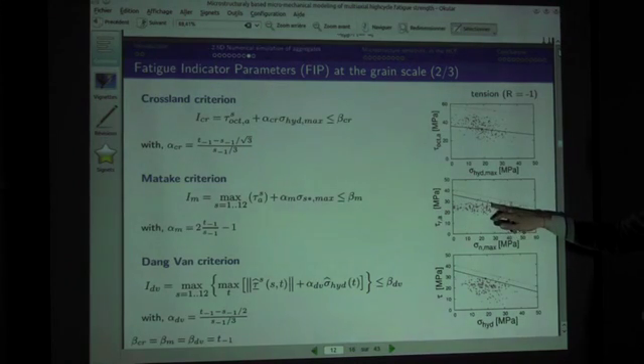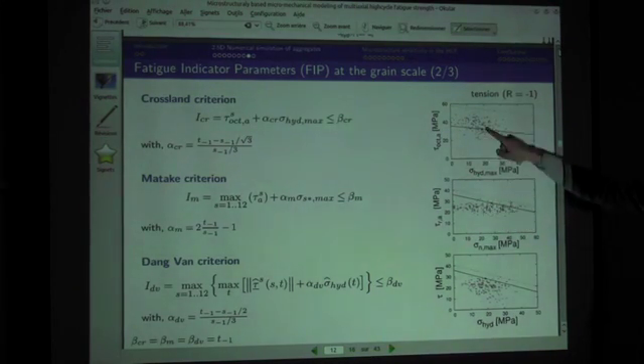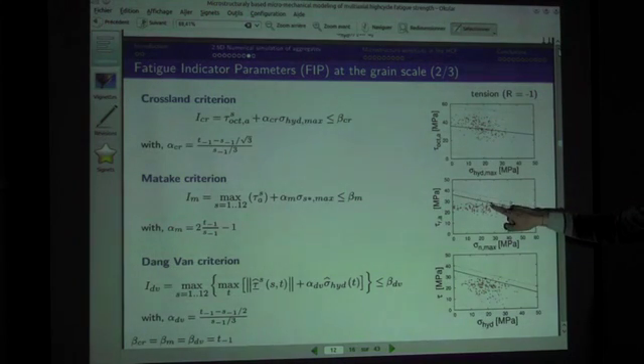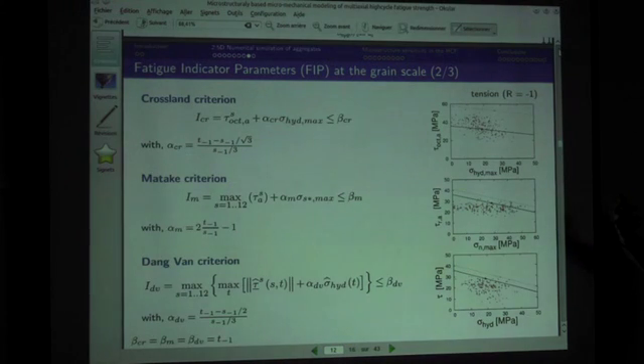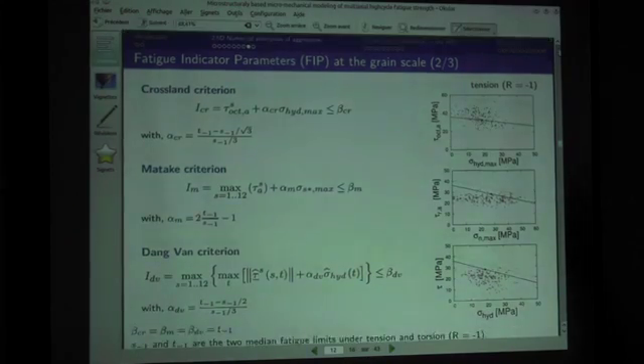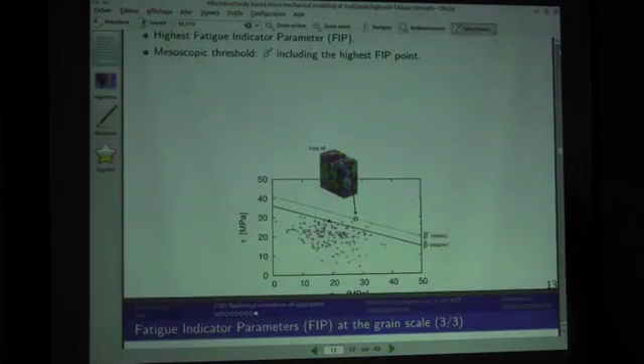And in particular, what you can see is that the mean stress here, for example, the black dot which is here, you have some grains which are not below the threshold of the material. You have some grains which are beyond this threshold. So it's more or less normal because this response is a homogenization point that is obtained from the macroscopic stress loadings. And when you look at the small dots here, you can build a new threshold, which will be a threshold for the mesoscale. So you need to introduce another parameter or another threshold here.